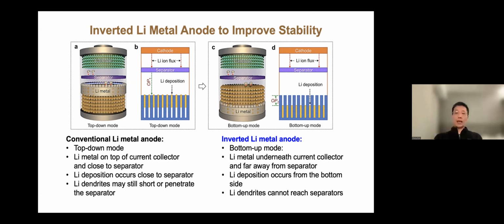What we found, and Cui Yi in his earlier publication also found, is that if you put down a little bit of these 3D conductive skeletons, it can effectively prevent the growth of lithium dendrite. Number two, what we found in this electrical field, when you plate the lithium metal from a cathode to anode, is that the lithium deposition will occur at the bottom. It does not really occur next to a separator. So even though there's a tiny bit of dendrites, they don't first come in contact with the separator, they don't penetrate, they don't short the separator.